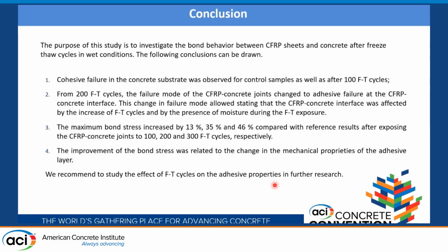In conclusion, the purpose of this study is to investigate the bond behavior between CFRP sheets and concrete after freeze-thaw cycles in wet conditions. The following conclusions can be drawn. Cohesive failure in the concrete substrate was observed for control samples as well as after 100 freeze-thaw cycles. From 200 freeze-thaw cycles, the failure mode of the CFRP concrete joints changed to adhesive failure at the CFRP concrete interface. This change in failure mode allowed stating that the CFRP concrete interface was affected by the increase of freeze-thaw cycles by the presence of moisture during the freeze-thaw exposure.